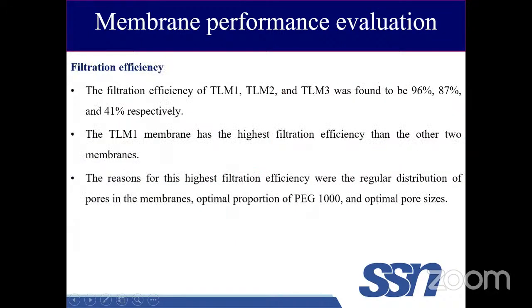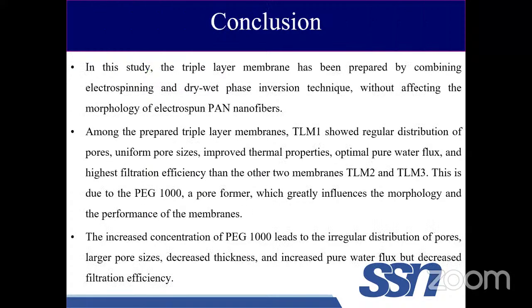Based on the results, we found the filtration efficiencies for TLM 1, 2, and 3 are 96, 87, and 41. So from the results, we found TLM1 to be a suitable candidate for filtration application. With this study, we prepared a triple layer membrane which has more functional property than the earlier study, with improved functionality as well as improved strength.